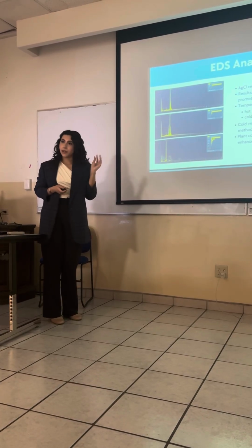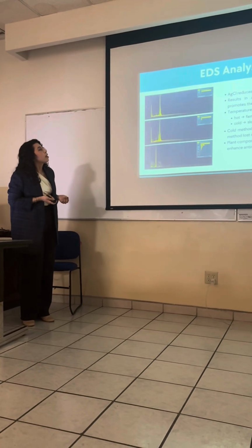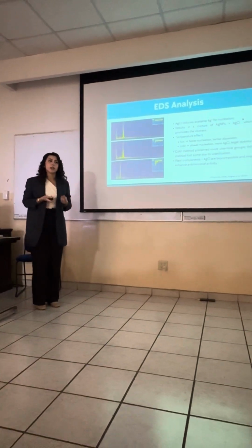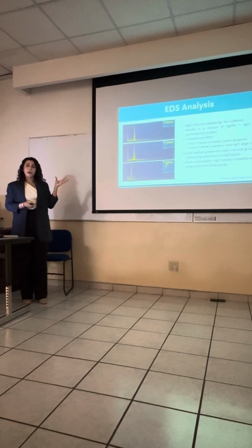They stated, and this is what I based my results on, that when chlorine is in presence of silver or vice versa, they tend to bind together. They go along well, so they tend to form silver chloride, which reduces the available silver ions that, instead of nucleating, bind with chlorine. This results in a mixture of AgNPs and silver chloride, which promotes clusters. Therefore, we can assume that this is a reason why, since we didn't sonicate the nanoparticles just before the DLS study, we got results with particles above 100 nanometers.